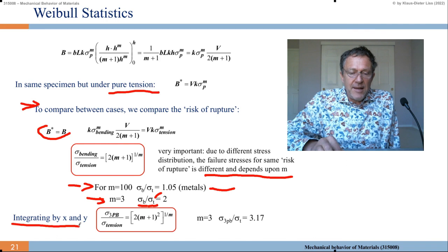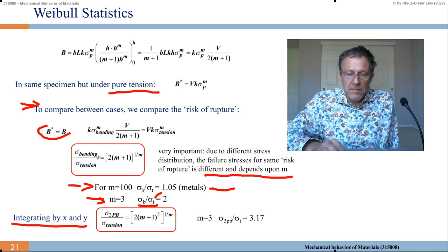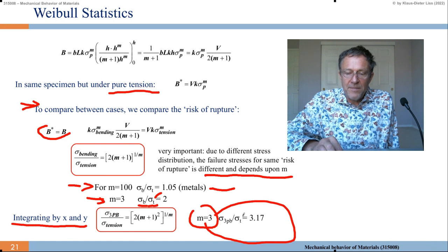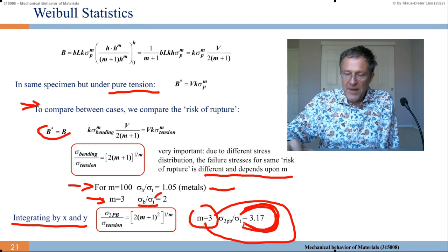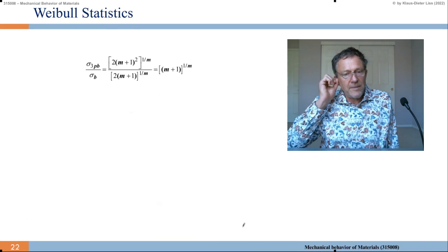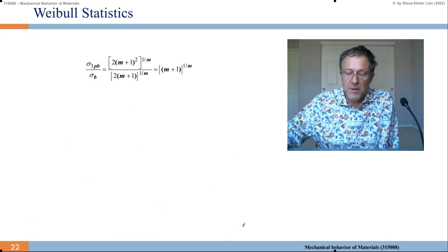And we can integrate that over x and y. So sigma 3 point bending and sigma tension becomes this formula here. Same formula. So for m equals 3, then sigma 3 point bending over sigma tension is 3.17. So I can make the stresses 3 times higher than in the pure tensile experiment. What I want to say, it depends very much on the geometry of the loading.